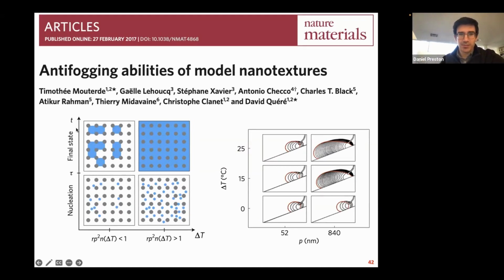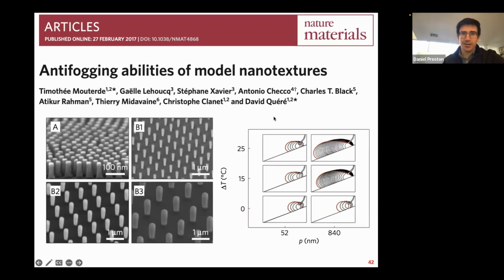And so they say in the plot here on the left that the left column represents a smaller structure. We will have nucleation within fewer of the unit cells. And that means that we will have less adhesion due to these full unit cells filled with liquid. And on the right, they show some traces of droplets during experiments where the smaller pitch, even at elevated temperature differences relative to room temperature, still limits the maximum droplet size compared to the larger pitch in the column on the right. They did this in the clean room.